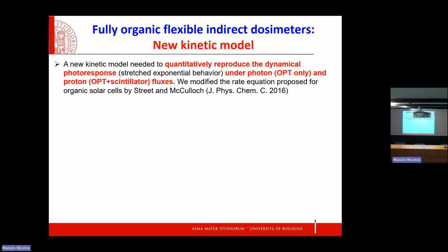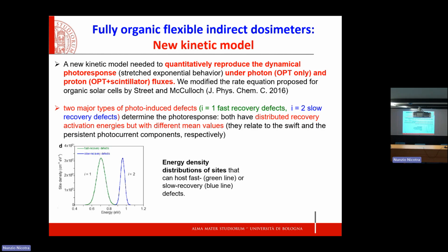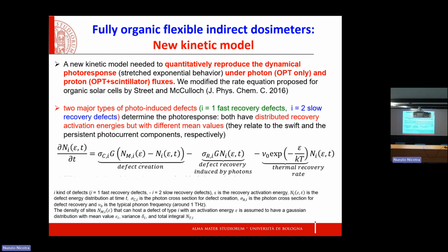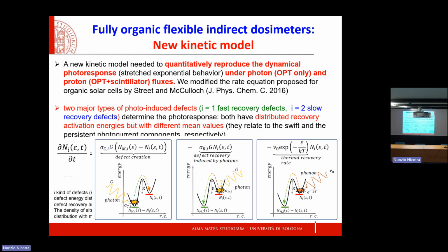In fact, we developed a simple kinetic model, simply taking into account the presence of two differently distributed trap states that have different trapping times. One is fast and one is slower. And if we model the presence of these two narrow distributions of defects, we can really see, this is the basic model, that under irradiation, we create the defect or we activate the defect. That is something we still do not know. We're still trying to understand if the radiation creates the defects and then everything happens, or activates them. And that is what happens. So you either create or activate the defect, and then you have all the recovery of the defects that can be induced by the photons or simple thermal recovery.